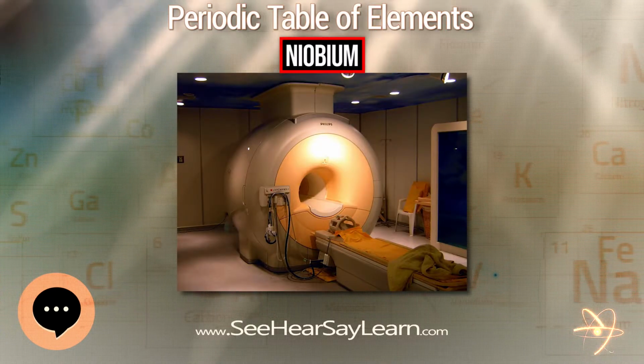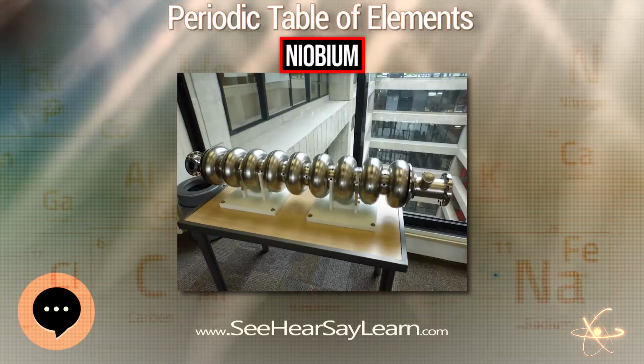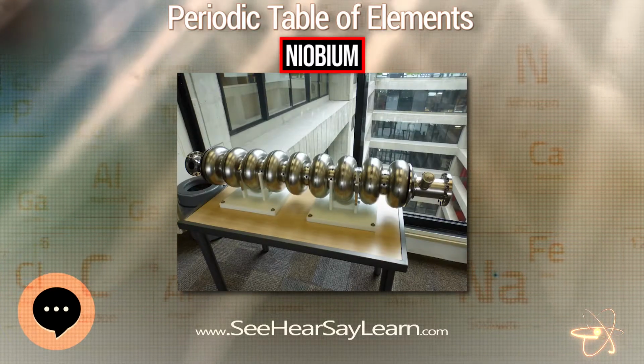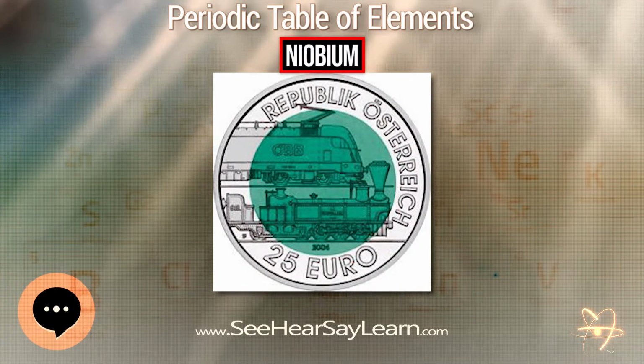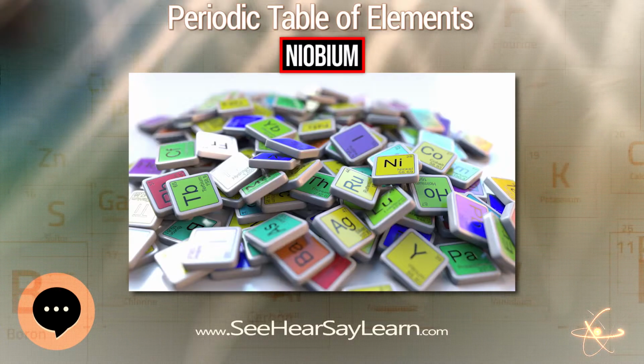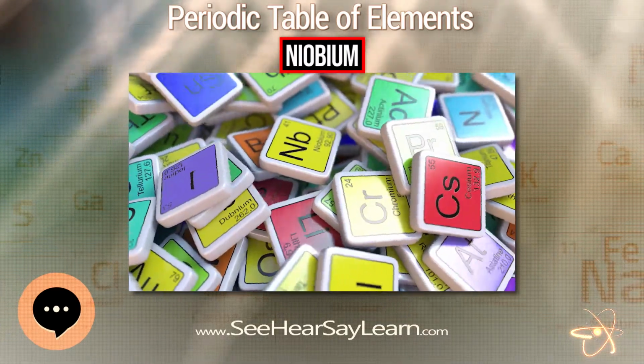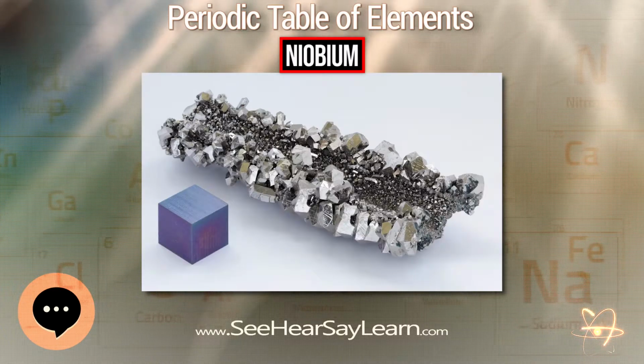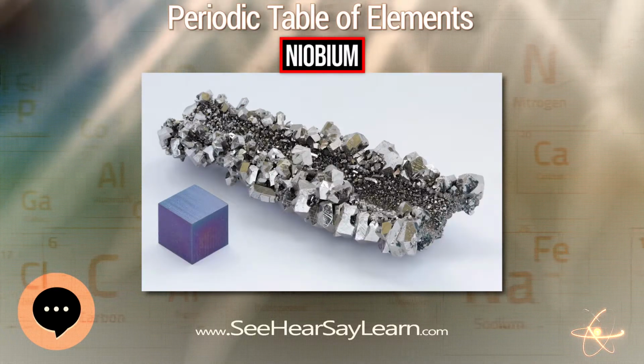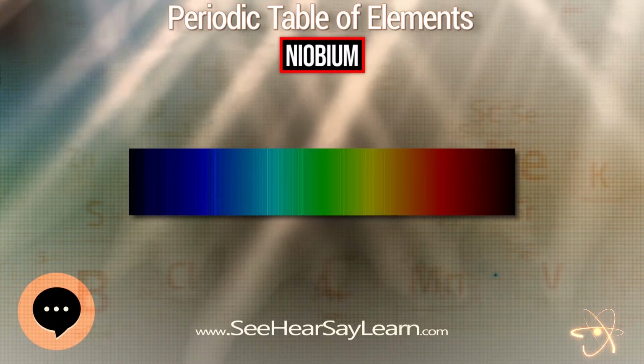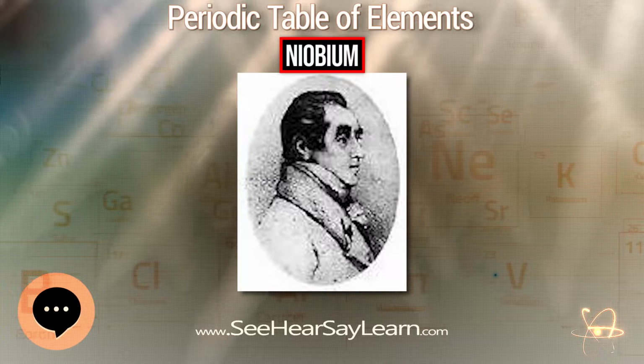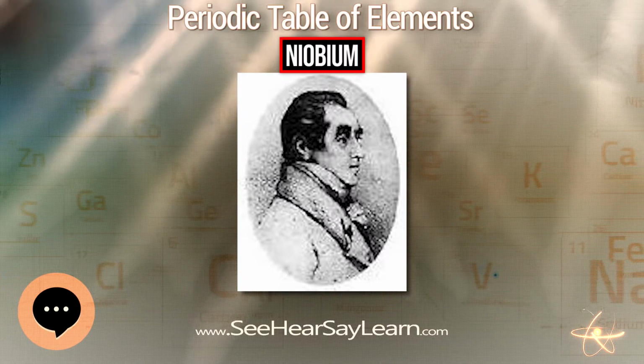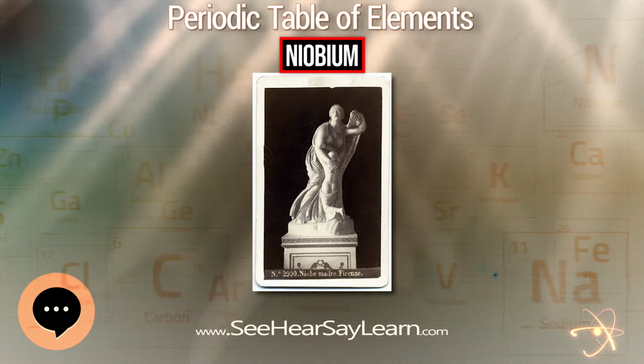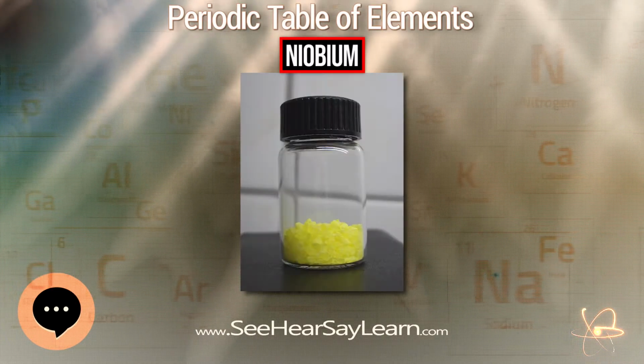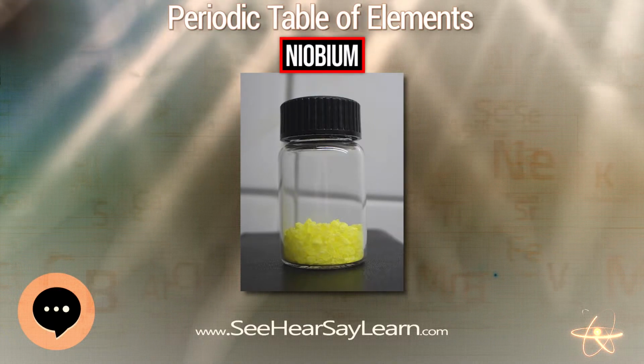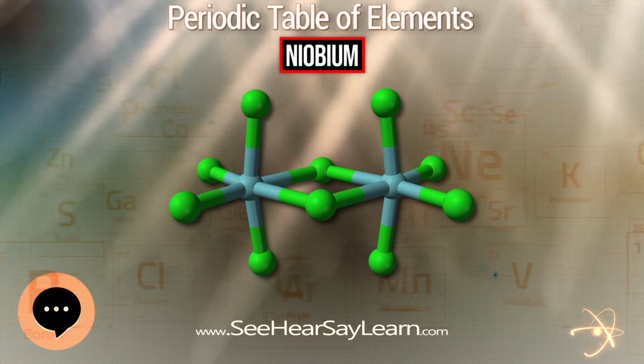Wah Chang had an inventory of hafnium, refined from nuclear-grade zirconium alloys, that it wanted to put to commercial use. The 103rd experimental composition of the C-series alloys, Nb10Hf1Ti, had the best combination of formability and high-temperature properties. Wah Chang fabricated the first 500 lb heat of C103 in 1961, ingot to sheet, using EBM and VAR. The intended applications included turbine engines and liquid metal heat exchangers. Competing niobium alloys from that era included FS85 from Fansteel Metallurgical Corp., Cb129Y from Wah Chang and Boeing, Cb752 from Union Carbide, and Nb1Zr from Superior Tube Co.